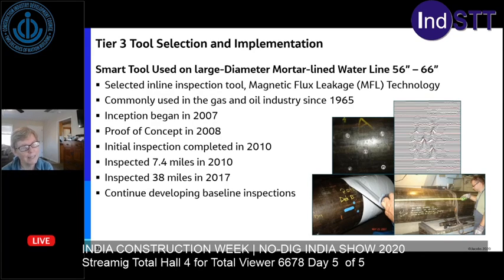If you look at the pictures on the right, you'll see the top two. One is a steel pipeline with 5 dents, or actually indentations, representing corrosion in there. What the MFL tool does is when you drag it through the pipeline, it magnetizes the pipe and it creates these signatures. If there's no loss in corrosion on the pipe, the line is straight. But as you can see, there's 5 areas of corrosion on the left, and you can see those 5 areas of corrosion depicted on the squiggly lines on the right.